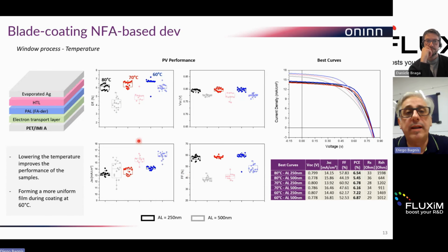Another part, and I believe is pretty interesting, is the behavior of the temperature during the coating. These are the blade coating results with a non-fullerene acceptor. And it's pretty interesting that when you reduce the temperature, in our case and with our condition, you not only improve the performance slightly, but you also have a better standard deviation in the results.